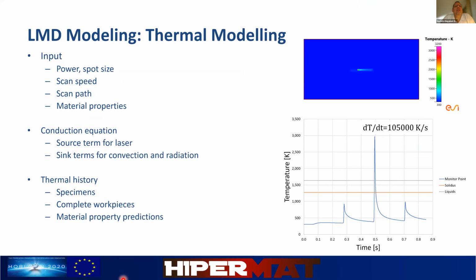For the thermal modeling, when we look at the melt pool models, we are looking at a very localized model. So looking at the melt pool and the specifics of the details of that region. But when we look at the thermal model, we are interested in capturing the thermal history of larger deposits, even the complete part if needed. So in this case, the power, spot size, scan speed, scan path are very important in addition to material properties. We basically solve the conduction equation, which includes a source term for the laser source, as well as sink terms for convection and radiation. What we get is the thermal history as a function of the deposition strategy. In this case, we see a diagram showing at a certain point 3 peaks.